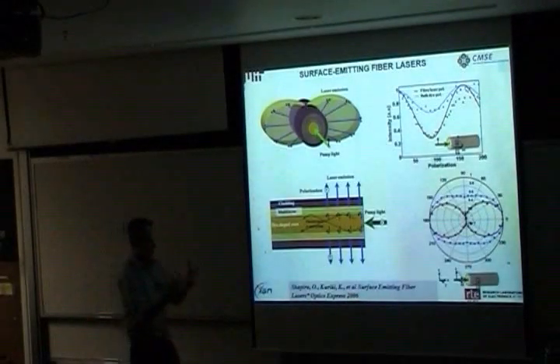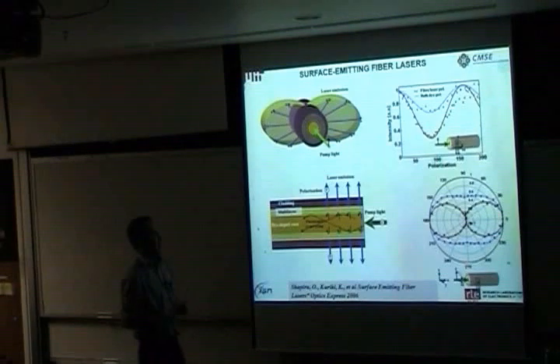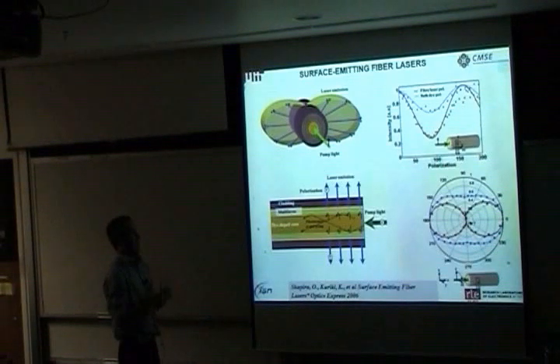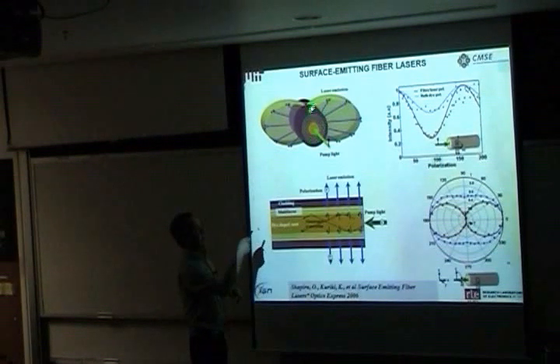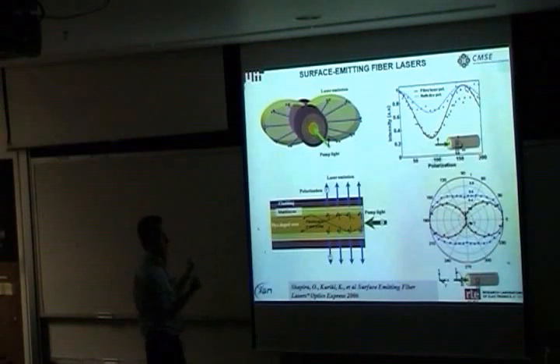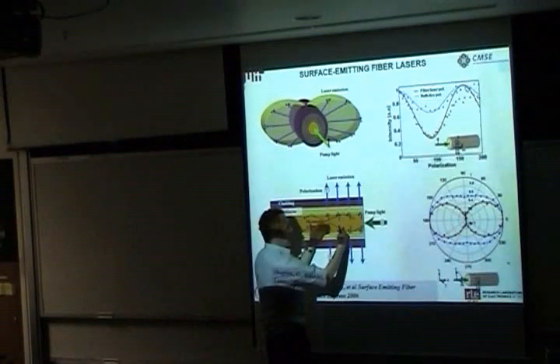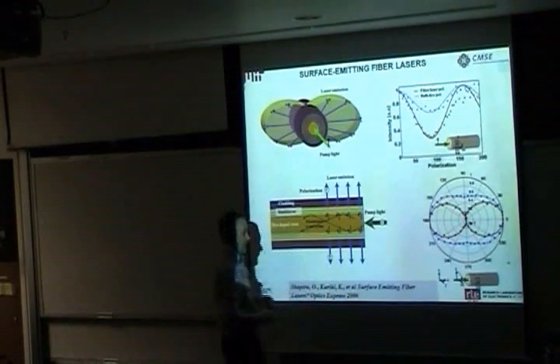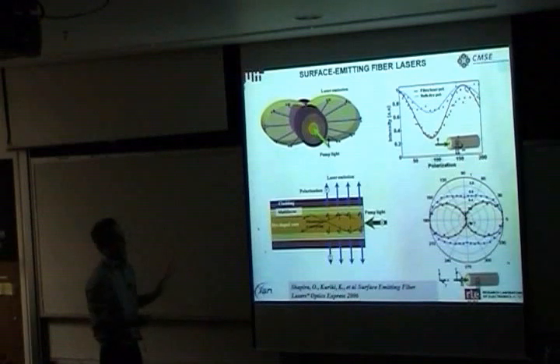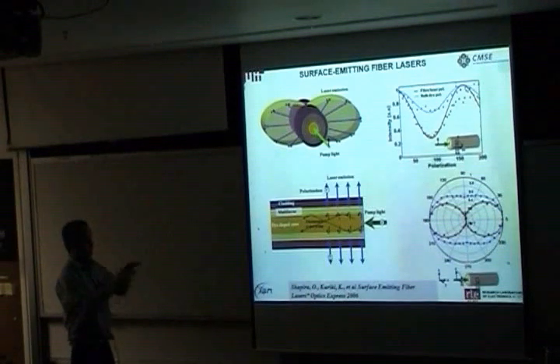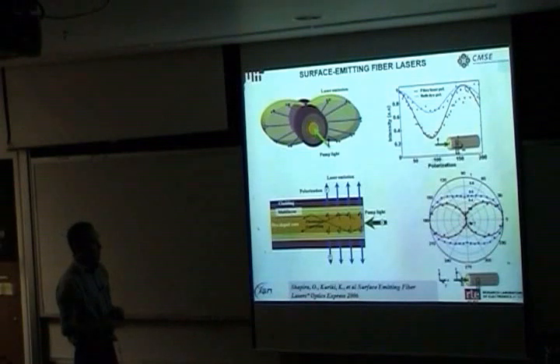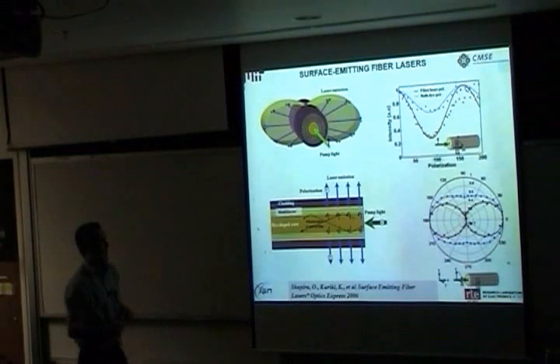So now I'm going to start connecting some of these individual pockets of information and trying to create things that are more complex and more functional. We talked about having an annular or cylindrical mirror. Well, here's what happens when you put a gain medium inside. Once you do that, you actually get optical feedback now in the radial direction. And so you then pump this optically, and what you could get is, in fact, lasing action in the radial direction. This is interesting. This is the first fiber that is actually a surface-emitting fiber, a vertical surface-emitting fiber structure.